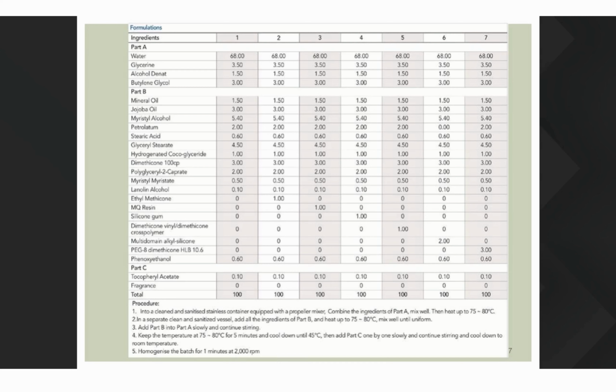But specifically what I'm looking for is a little bit past, right below lanolin alcohol, there's the ethyl methicone, which was the material that I showed that had very low surface tension with a small amount added. It doesn't have an alkyl on there that's large, so it's not going to change rheology, but it is going to lower surface tension, so we can look at that difference.